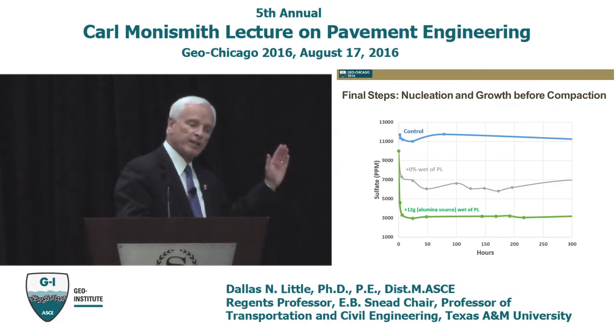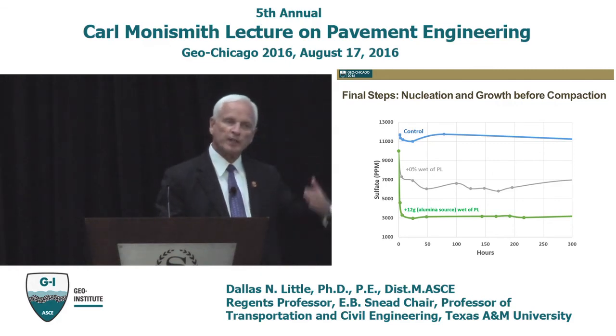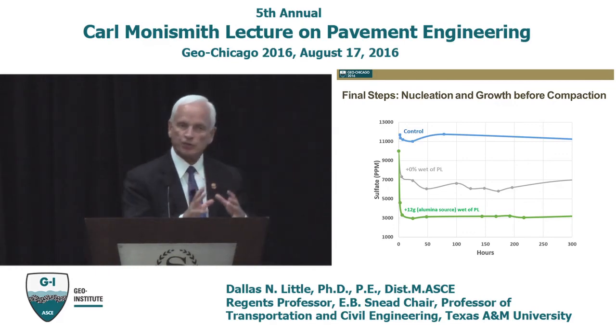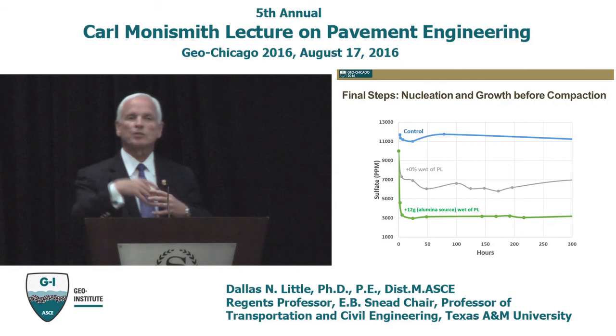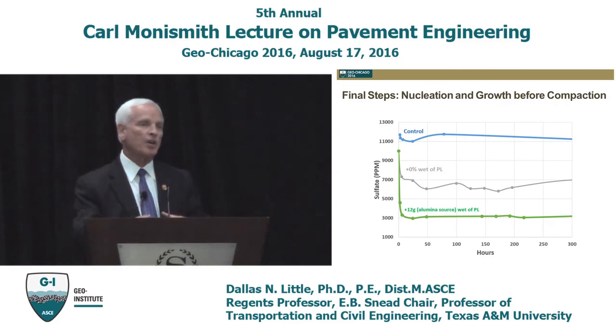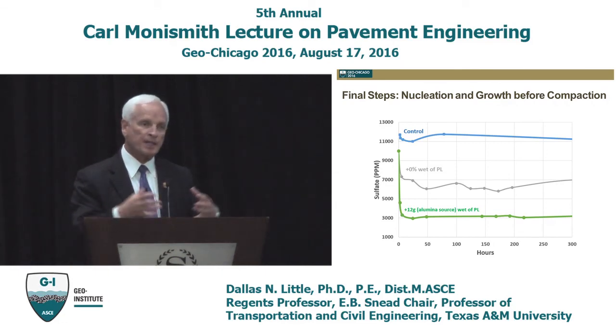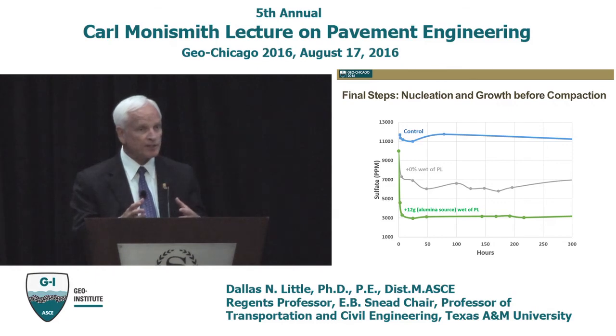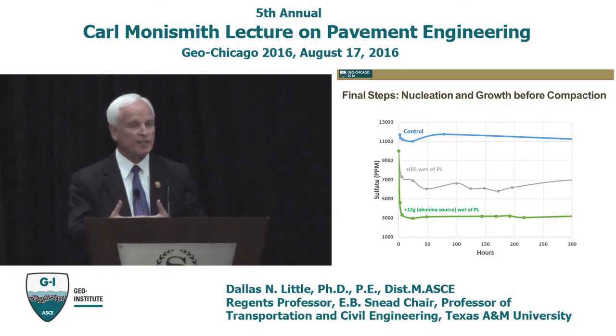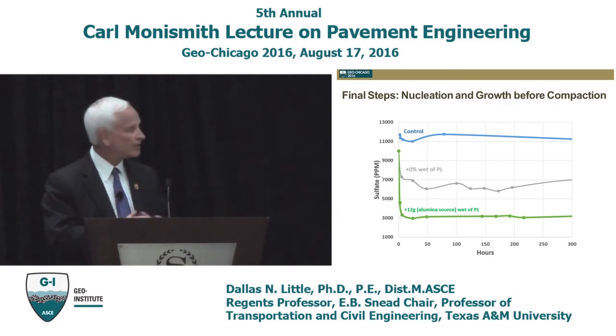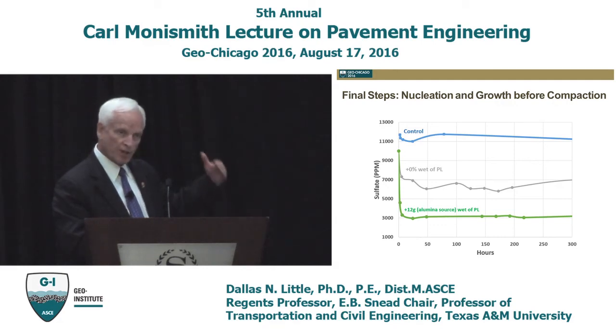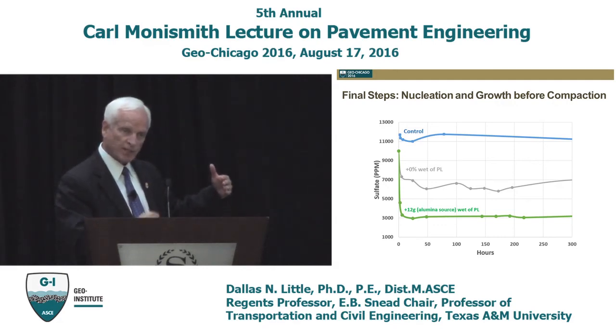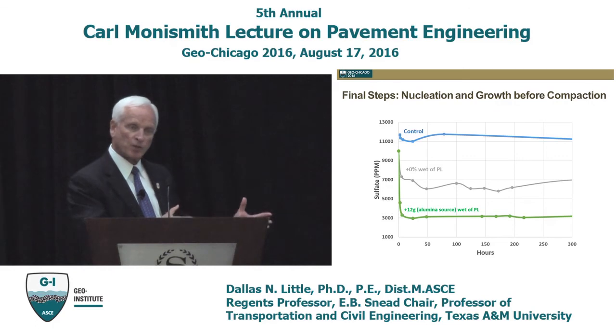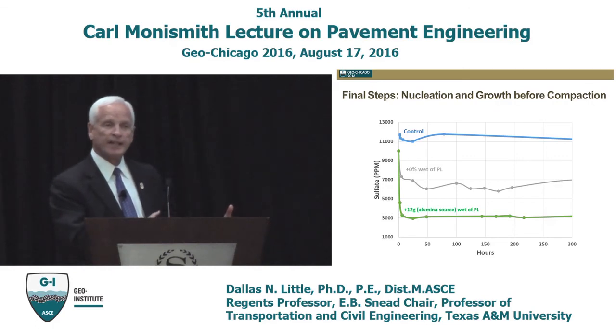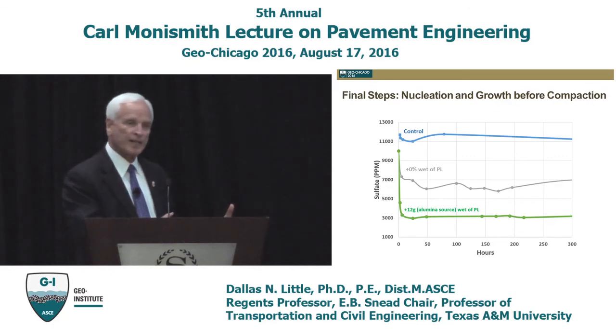See, ettringite is calcium aluminate sulfate hydrate. The alumina comes from the soil, and it's not going to be released until we solubilize alumina at that high pH, and that's a slow process. So how do you get this? How do you trick it? The way you trick it is you add a source of soluble alumina. And you can get some sources of soluble alumina that are readily available and that are quite reactive.